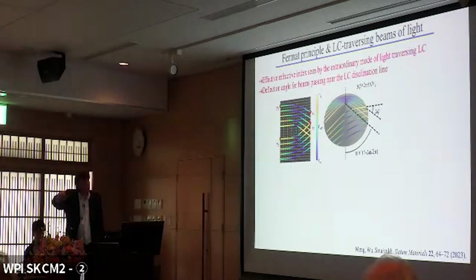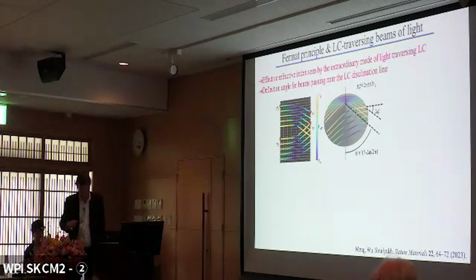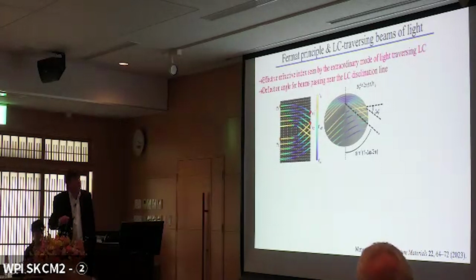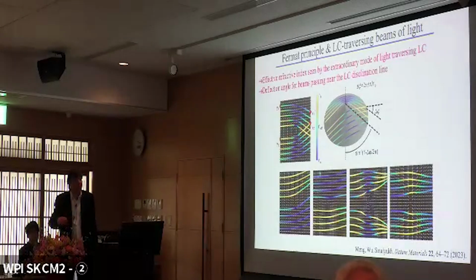line perpendicular to the screen in here, in this geometry, the beams of light will be deflected because when traveling from point y1 to y1 prime, due to the Fermat principle, light will take the trajectory that gives the shortest amount of time to travel from one point to the other. And this gives us effectively this cone geometry that you can see depicted in here. We have the effective lensing of light by this vortex line.